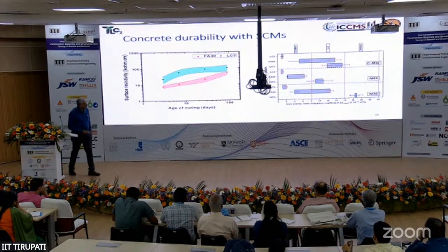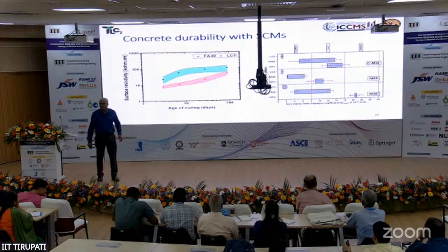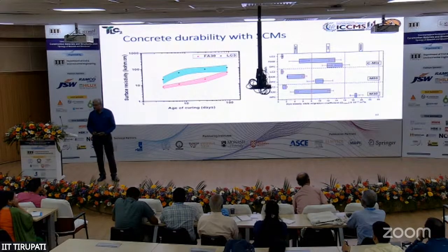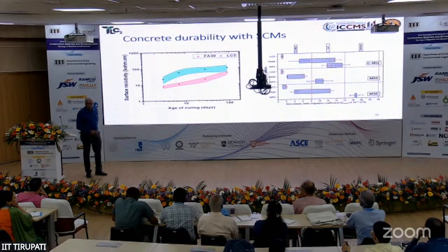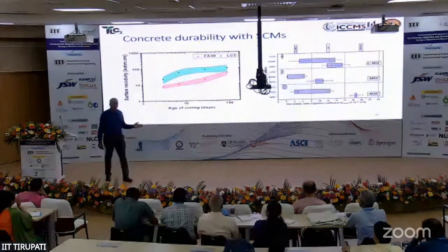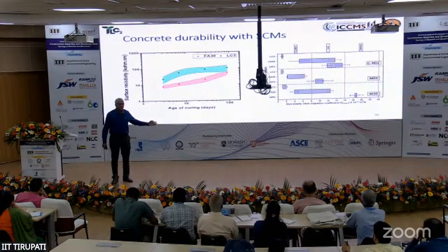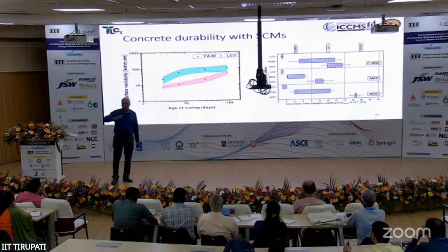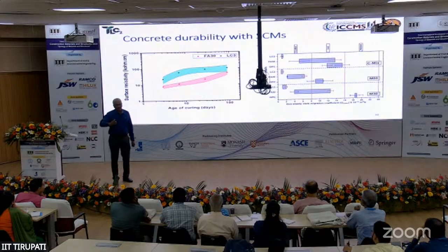And if you look at the non-steady state migration coefficient, which is today used to do a lot of durability design in chloride exposure environments, you clearly see that even for low grades of concrete like 30 MPa, your LC3-based system is able to reduce the non-steady state migration coefficient to less than 2 × 10^-12 square meter per second, which is actually an acceptable limit for a very high quality concrete, right?